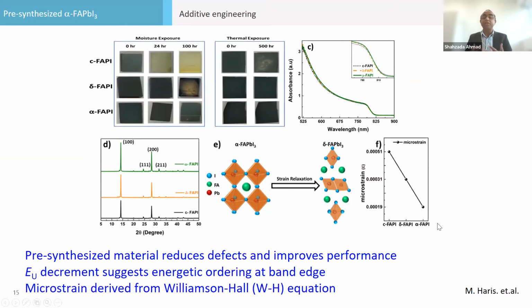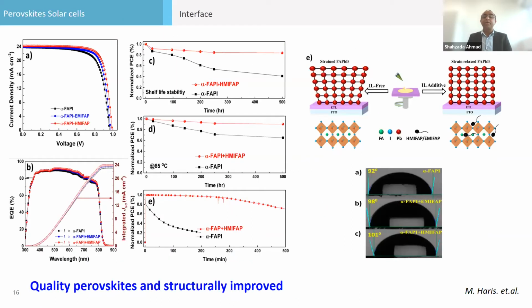So the Urbach energy decreases. If the Urbach energy decreases, our voltage deficit will decrease, so we can obtain a higher voltage. So this all suggests that with this powder methodology, the energetic ordering is increasing, it is more hydrophobic, and the crystal ordering is close to perfect here.